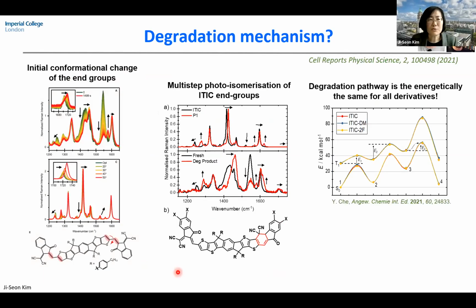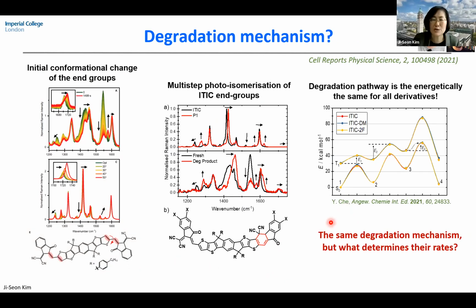The change we observed in ITIC originates, again, from the rotation of a movable end group in ITIC. When it flips over, of course, it can form photoisomers in the molecule, which we also observe as a byproduct. The degradation pathway is energetically the same for all these three NFA materials. But as I mentioned, it shows different degradation rates. So what determines this degradation rate? When we put a fluorinated, very strong electron withdrawing unit in the end, it slows down this degradation process.